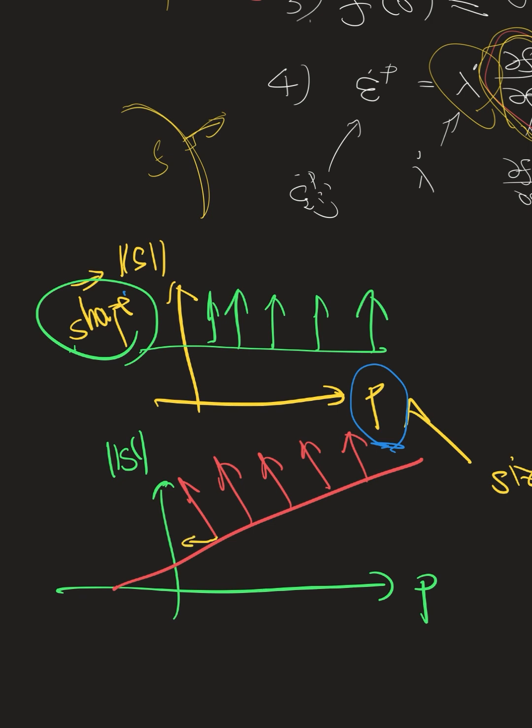Another portion is in this direction. So if I create plastic strain for a given change in P, I actually need a portion of it changing the S. Converted into a kinematic view, if I have plastic strain in shear, if I change the shape of the material permanently, I'm also going to change the size permanently.